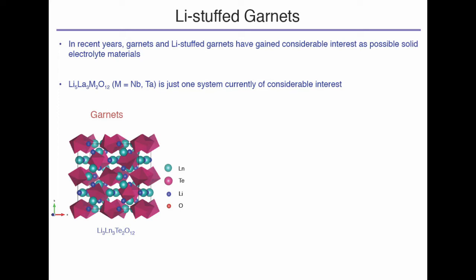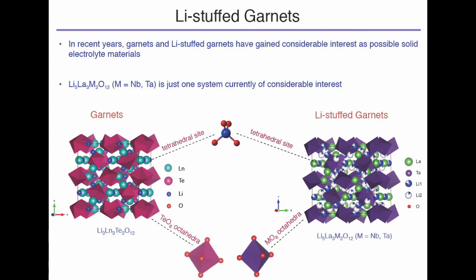So this is, on the left, an example of a basic lithium-based garnet type structure. In that structure, you have the lithium that sits on a tetrahedral site, and then you have these MO6 octahedral sites. In a lithium-stuffed garnet, such as this one here, Li5La3M2O12, where the metal can be either niobium or tantalum, you still have this tetrahedral site for the lithium, but you also have a distorted octahedral site where the additional lithium can go in. So the idea behind these lithium-stuffed garnets is you want to create an ion conductor by pushing as much lithium into that structure as possible and forcing it to conduct lithium ions.